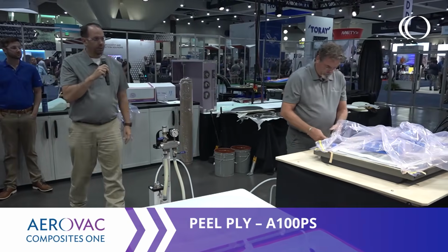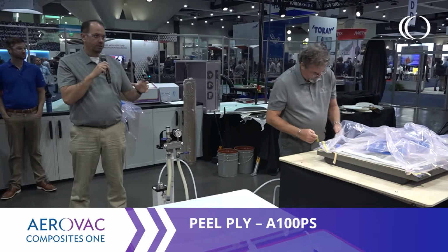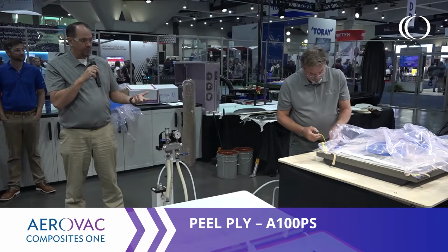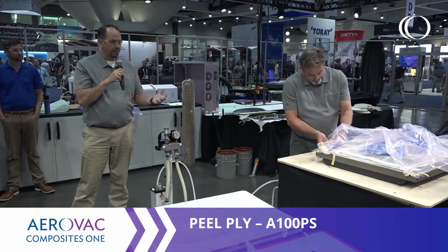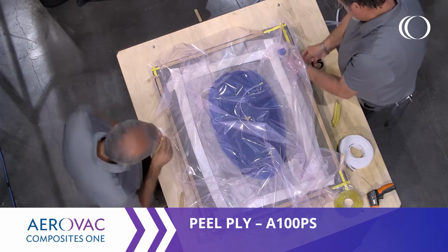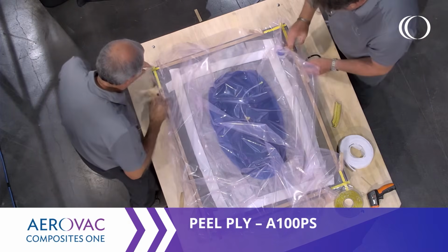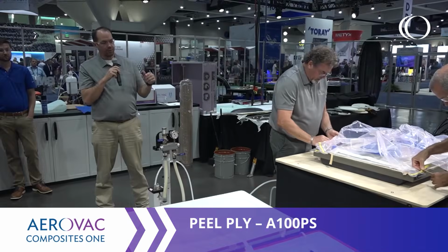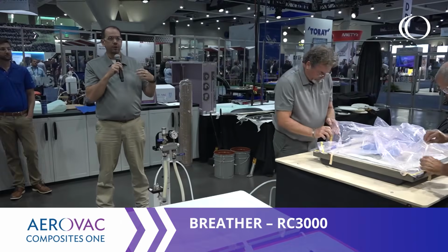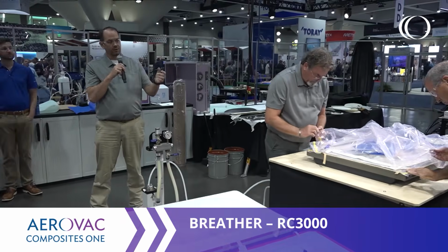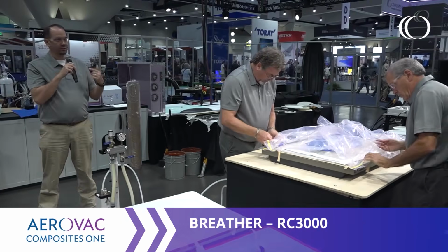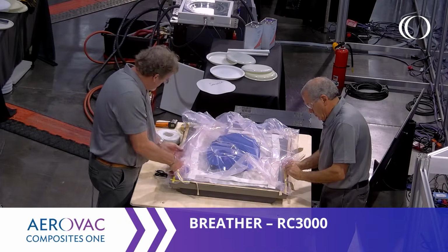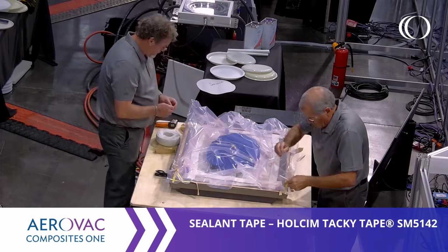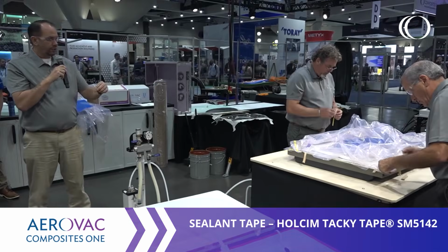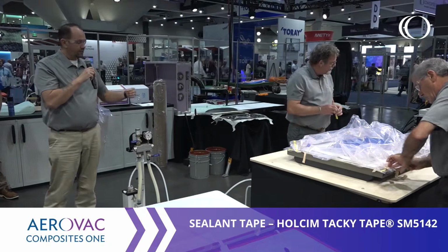That nylon peel ply helps with resin distribution and also part impressions. So if you need a surface that is going to have some secondary bonding, that is generally where we'll see the most usage for peel ply. Then, around the periphery of that, you'll see a 10-ounce nylon breather to help with air communication. Notice that they have overlap, so you have consistent airflow across the part. Outside of that, they've got the Holcim 5142 sealant tape, good to 400F, so they can get a good, tight, airtight seal.